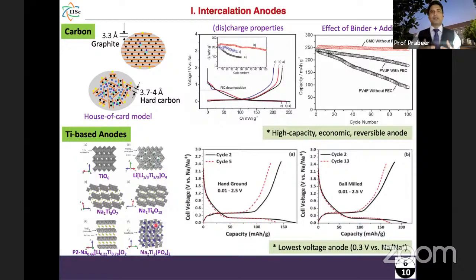titanium intercalation redox system. One example shown here is Na2Ti3O7. This material basically works as the lowest voltage anode material, operating around 0.3 volt versus sodium, and it gives capacity around 150 milliampere per gram. So very, very decent. Now, if we do the ball milling, we can further enhance the capacity to close to 200 milliampere per gram. Initially we have Na2Ti3O7, and when we try to insert 2 more sodium, it can become Na4Ti3O7, and thus 2 sodium can come in and out, and the 2 electron reaction can give 200 milliampere per gram capacity. So these are 2 classic examples of how we can use intercalation based anode for sodium battery.